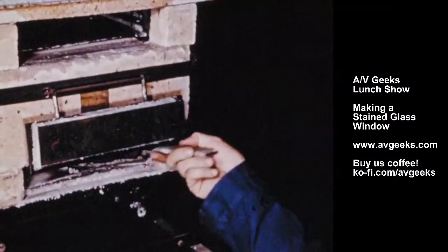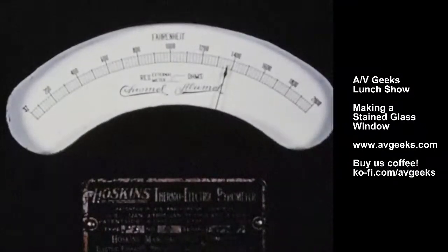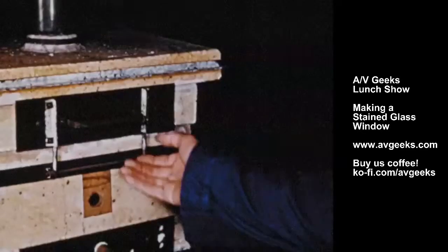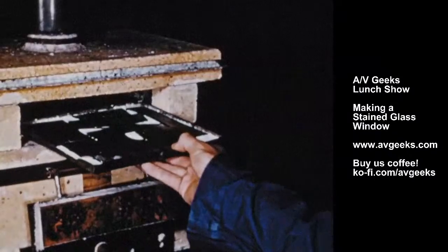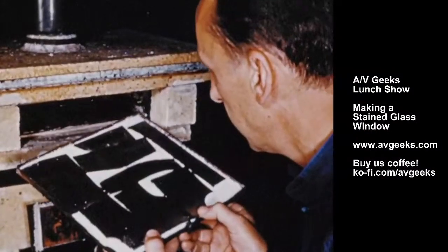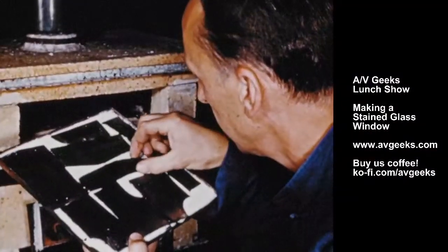The tray is then returned to the annealing chamber, which becomes a cooling chamber when the heat is turned off. The glass must be cooled slowly to avoid cracking. Not for several hours can it be safely removed from the kiln. In fusing with the glass, the paint has lightened in color, adding subtle gradations of tone to the natural quality of the glass.